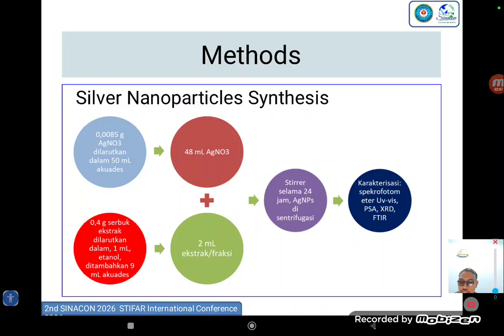Silver nanoparticle synthesis. For the silver nanoparticle synthesis, we added 2 milliliters of the 4% extract solution into 48 milliliters of 1 millimolar silver nitrate solution. This mixture was continuously stirred for 24 hours at room temperature. Afterward, the synthesized nanoparticles were characterized using UV spectrophotometer, FTIR, XRD. Finally, we evaluated all samples for their antioxidant activity.